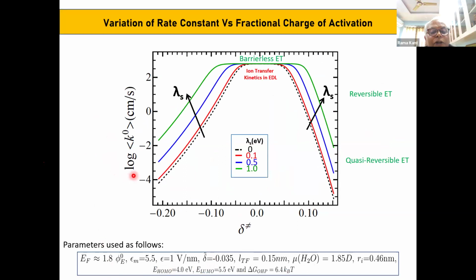So here I am plotting the log of the standard rate constant, which has dimension centimeter per second, the electrochemical rate constant. And then you have the fractional charge. When we plot with respect to this, we have a maximum, like in Marcus theory also you have some kind of maximum. When you are playing with the reorganization energy, here it is the difference of work function and my FMO energy, which will include reorganization.